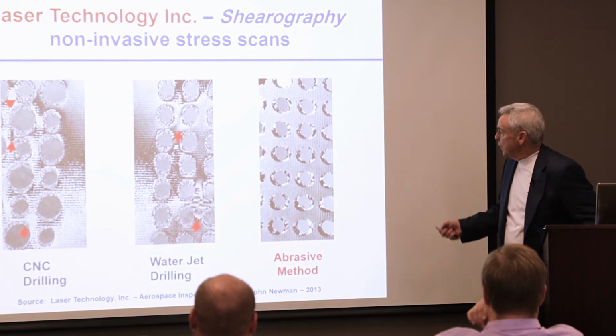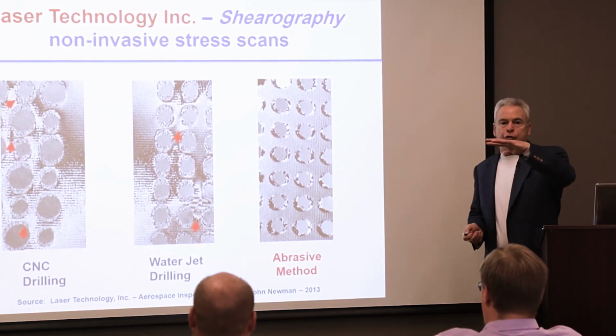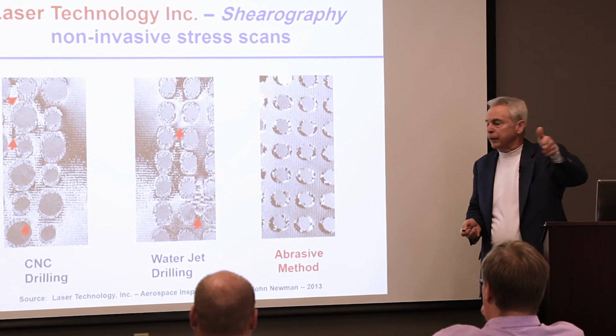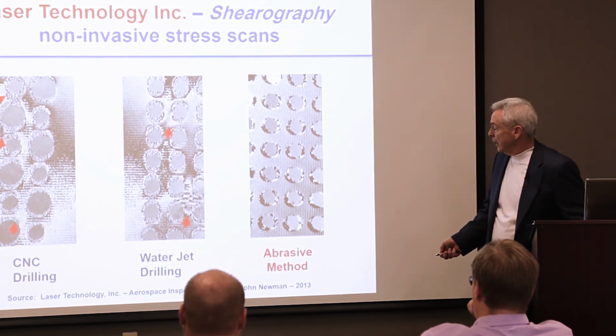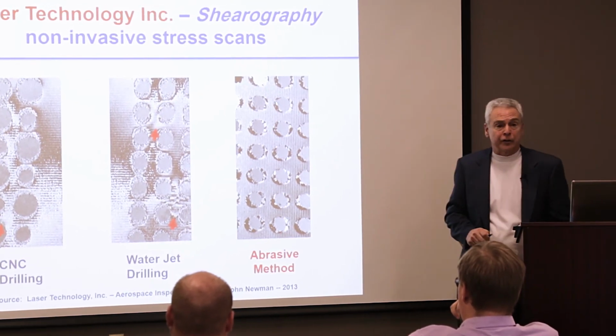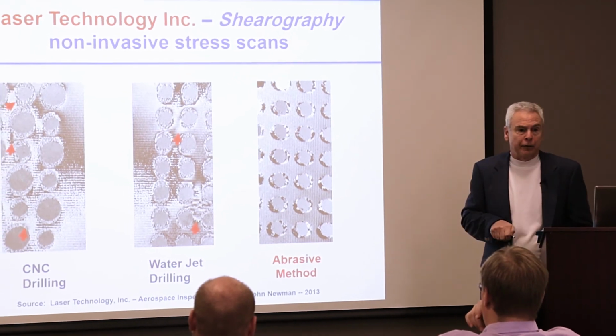However, if you look at it with the abrasive method, because of the gentle approach that's taken as we scan gently through to create those holes, we don't see a lot of those stresses. Some, but very, very minor. Okay.